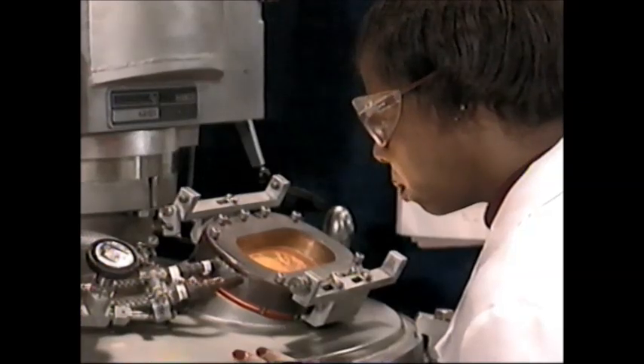When the polysilicon mixture melts to the consistency of water, the seed crystal is lowered slowly into the molten silicon, just past the point of contact. It is then slowly pulled upward as the seed and molten silicon are rotated in opposite directions. To draw the silicon crystal from the crucible, the mixture must be kept very near the freezing temperature of molten silicon, or about 1410 degrees centigrade.